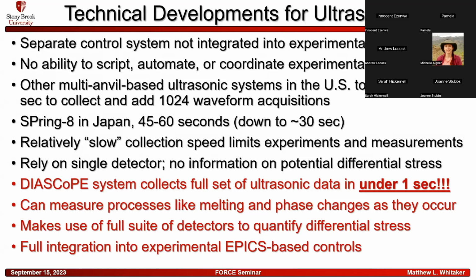So when we built this system, it collects a full set of ultrasonic data in under a second. It can measure processes like melting and phase changes as they occur. Again, this goes back to something that I talked about earlier with the metal forging, where we can see the before and the after, but not the during. Now we're able to see the during because of the speed of this.